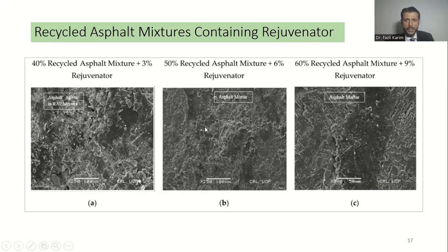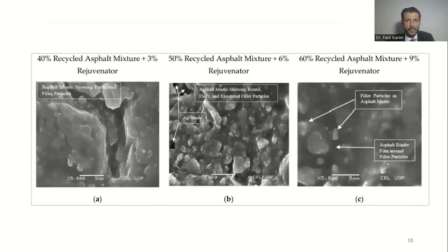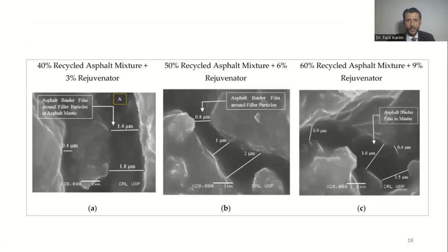All these images show asphalt mortar gripping large aggregate and asphalt mixture. Similarly, these images show asphalt mastic, reflecting filler particles. Even flaky, elongated, and round filler particles can be seen, even with emptiness in the asphalt mastic. And here, asphalt binder film can be seen among the filler particles. Now, clear asphalt binder film thickness in each type of mixture is visible, ranging from 0.4 to 1.8, similarly 0.8 to 2, and similarly 0.4 to 1.6.